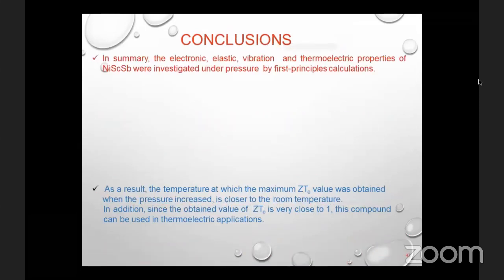As a conclusion, in summary, the electronic, elastic, vibrational and thermoelectric properties of this compound were investigated under pressure by first principle calculations. The mixture of heavy and light bands near the valence band leads to high thermopower and reasonable conductivity. The obtained results show that this compound is mechanically and thermodynamically stable. Theoretical analysis presented here predicts that this compound is a possible novel thermoelectric material with a low value of lattice thermal conductivity.